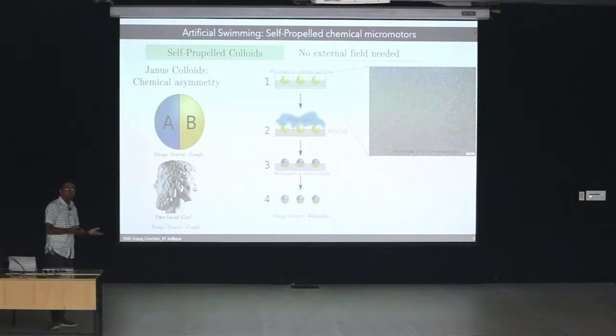There are multiple ways to create Janus particles, but one of the ways which is very popular and which we also use in our lab is to use physical vapor deposition or chemical vapor deposition. So we start with a monolayer of isotropic colloids. When I say isotropic colloids, these are particles which have the same functionality all over their surface. So we create a monolayer of these particles. This is a very nice monolayer of 5 micron silica particles which we prepared in our lab.